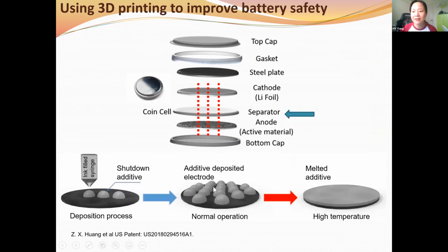So the last part, I want to show a very short part on the safety control that we designed. So we have made a temperature sensitive ink for a 3D printer and printed it on the membrane. So we have this spherical shape after we use the 3D printer to print this temperature sensitive polymer. And the temperature sensitive polymer will melt when the temperature goes above 90 degrees. And then when this polymer melts, it will become a slurry and then go into the pores of the membrane and block the pores.